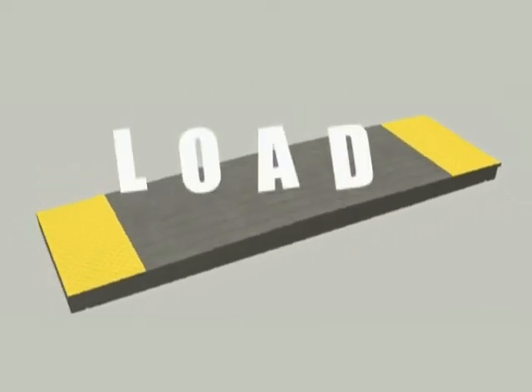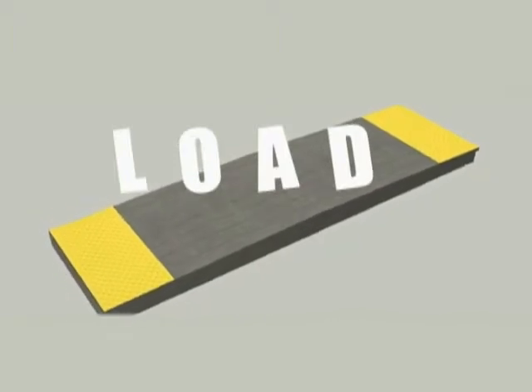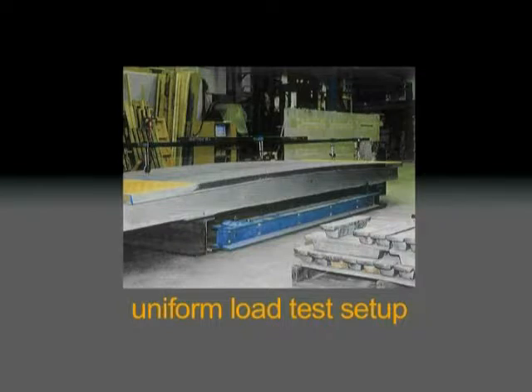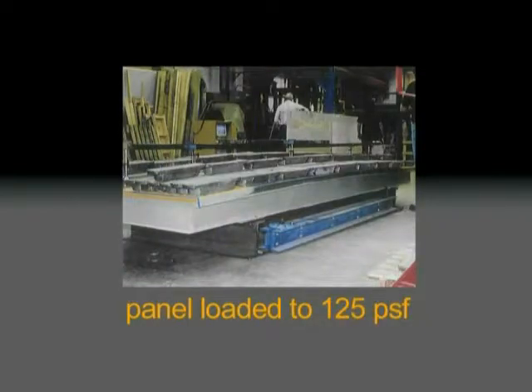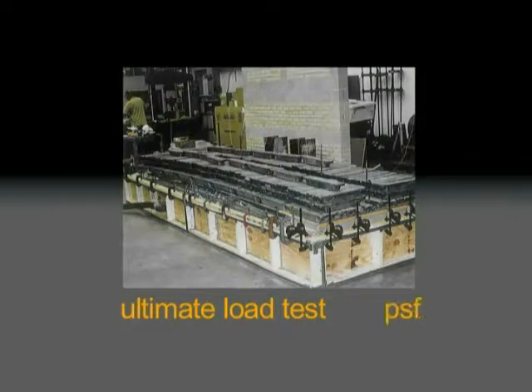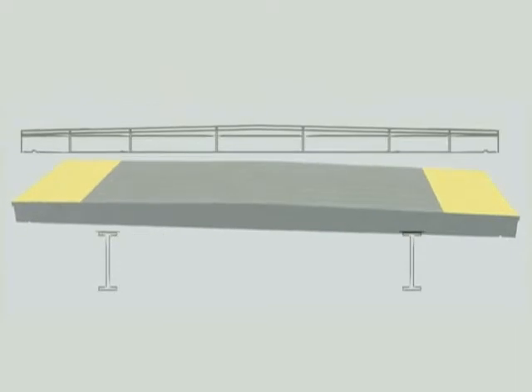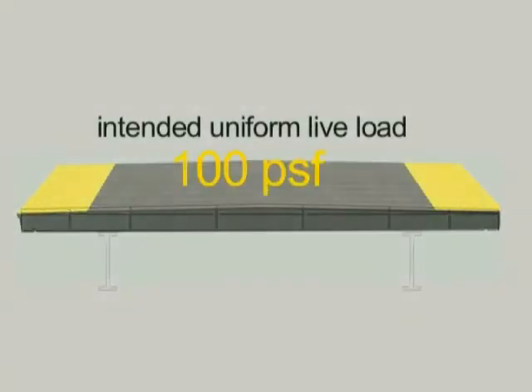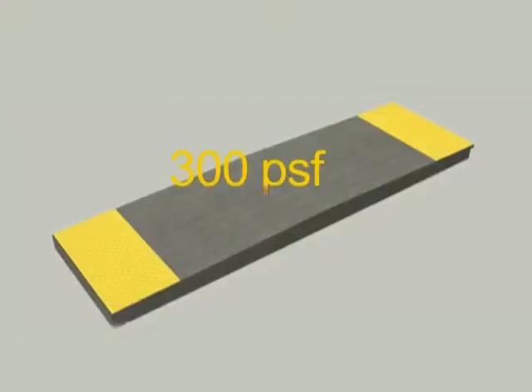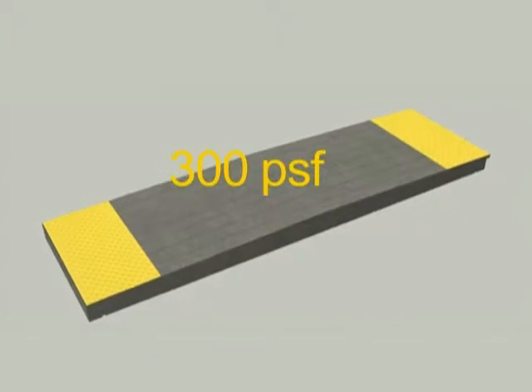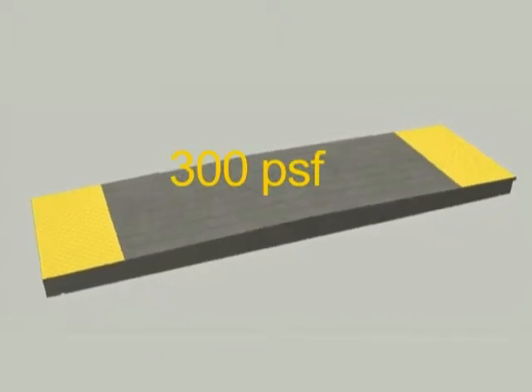The next test after doing the vibration testing was to do a load test on the panel, applying a uniform load in increments up until we actually failed the panel, got it to collapse. We applied these loads in 25 PSF, pounds per square foot increments, up to a uniform load of 300 PSF. The design load, or the intended uniform live load that should be applied to the structure is 100 PSF. Our intent was to load it to 3 times that amount and verify that it could take that load safely with a minimum amount of deflection.